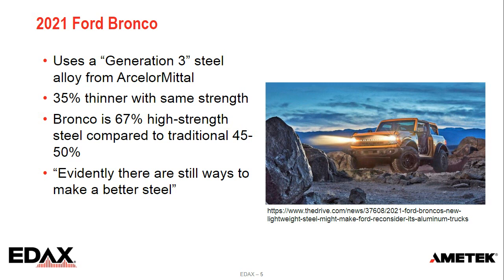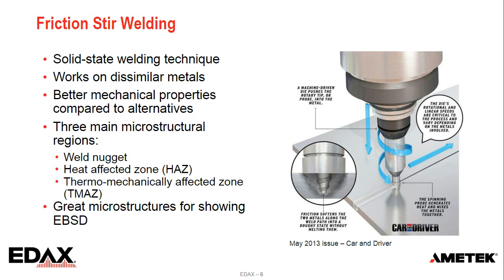So to start, I wanted to talk about some friction stir welding and show some examples from a steel sample. If you're not familiar with friction stir welding, it's a solid state welding technique. It's of interest for steels because it works with dissimilar metals, can be used to weld steel to aluminum, and the mechanical properties come out better compared to other alternative welding techniques. There are different microstructural regions, and they make really pretty pictures for EBSD, as you'll see. And you can see a little diagram here of how this goes, but again, the tool is pushed into the metal that's being joined. It stirs around, and the friction and the heat there, it describes it. It's a little hard to read the text on here, but it creates a doughy type structure. So it mixes things without melting. It's a solid state technique. And this is from Car and Driver magazine that covered friction stir welding a few years ago.